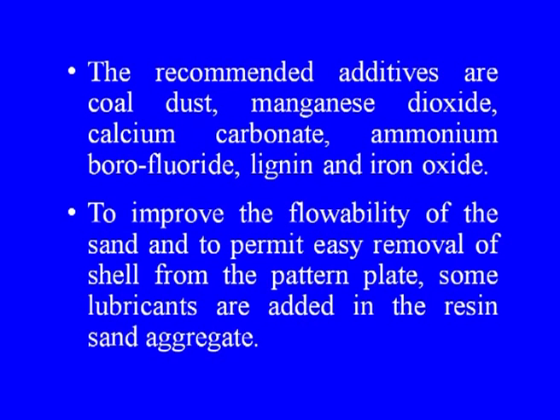Additives may be added to the sand aggregate to further enhance the surface finish of the casting, improve the strength of the mold, and develop resistance to thermal cracking and distortion. The recommended additives are coal dust, manganese dioxide, calcium carbonate, ammonium borofluoride, lignin and iron oxide. To improve the flowability of the sand and permit easy removal of the shell from the pattern plate, lubricants such as calcium or zinc stearate are added to the resin-sand aggregate.